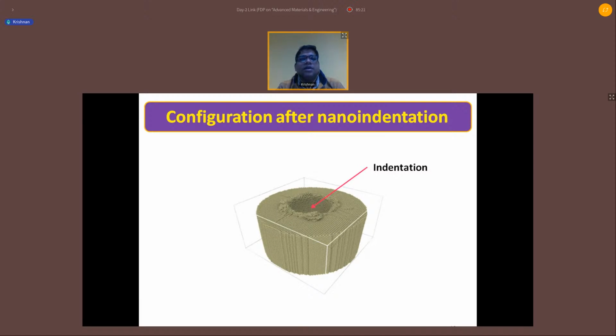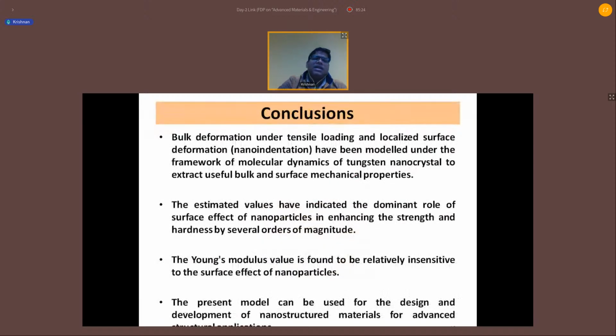And this is the conclusion. Bulk deformation under tensile loading and localized surface deformation have been modeled under the framework of molecular dynamics of tungsten nanocrystal to extract the bulk and surface mechanical property. The estimated values have indicated the dominant role of the surface effect of nanoparticles in enhancing the strength and the hardness by several orders of magnitude.